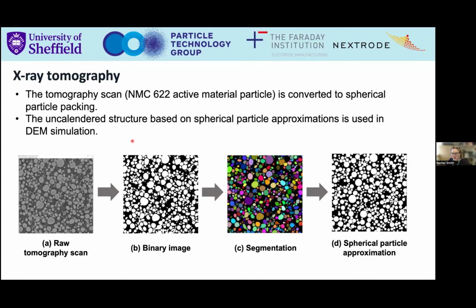So in order to apply this technique, we first have to understand what structures we have at the beginning. So we used tomography scans basically. We found some very nice databases. To start with, we used original databases of scans of electrodes. And then we segment the image, we turn that into a binary